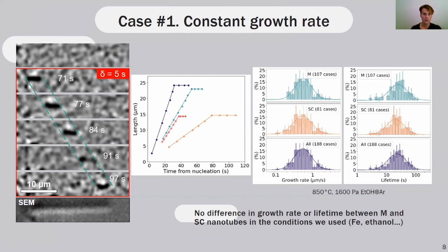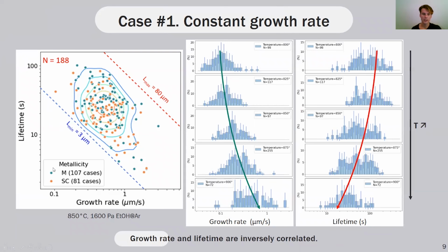The first case, which we observed in almost half of cases, is constant growth rate. You can see kinetic curves here, and you can see that tubes grow linearly until an abrupt stop. We found no difference in growth rate and lifetime between metallic and semiconducting tubes, in contrast with previously reported results. But it can be the result of us using different conditions, for example, iron as catalyst and ethanol as precursor. We also evidenced anti-correlation of lifetime and growth rate, which can be explained with temperature. So with an increase of temperature, growth rate tends to increase while lifetime tends to decrease.